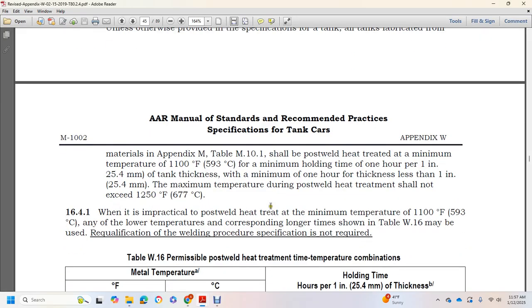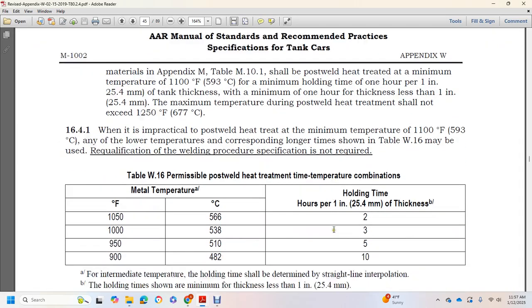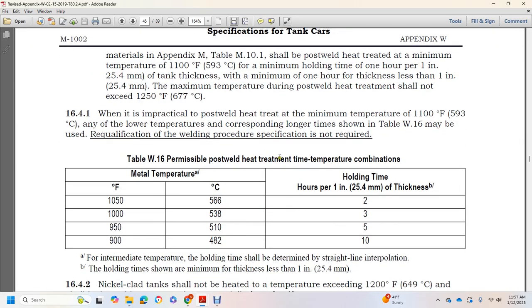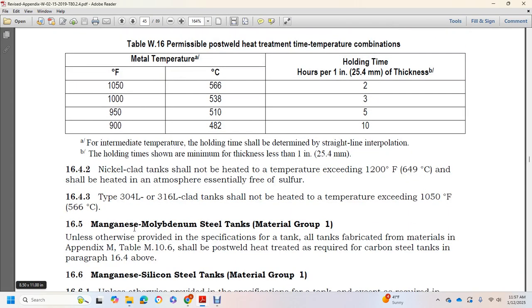When it is impractical to post-weld heat treat at the minimum temperature of 1100 degrees Fahrenheit, any lower temperature with longer times, per W16, may be used. Requalification of the welding procedure specification is not required. The permissible post-weld heat treatment time-temperature combinations are as follows, in degrees Fahrenheit: 1050, hold time of 2 hours; 1000, 3 hours; 950, 5 hours; 900, 10 hours.